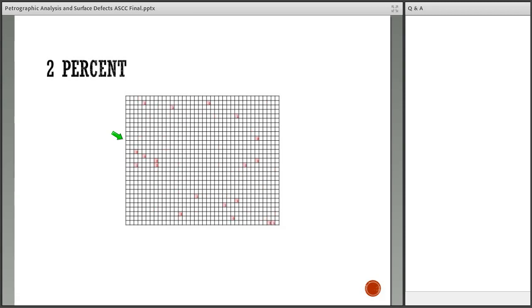At 2%, you start seeing areas where you have less and other areas where you have more. It becomes even more apparent when you look at 1%. Here again, this is a random generator. If you were to take a sample here, you can see that you have 2 pop-outs there. And when you send that to a petrographer, they might say, well, you've got a lot of pop-outs, but actually there's a lot of space here and here and over here where you don't have much